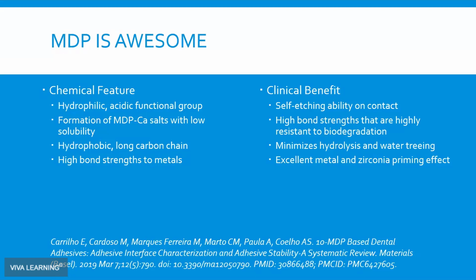Now, one key difference that has been shown is etched versus unetched enamel. Prepared enamel is fine, but with unprepared enamel, you'll see a dramatic improvement in bond strength if you etch the enamel prior to exposing it to MDP. The MDP calcium salts that are formed between the tooth structure and the adhesive have low solubility, which, as I mentioned earlier, helps to have high initial bond strengths that are resistant to breakdown. This long hydrophobic carbon chain minimizes hydrolysis, so you don't suddenly have whole fillings falling out. You don't have crowns just falling off for no reason. It's super stable due to the hydrophobic aspect of it. And of course, the high bond strengths to metal are exhibited in its tenacious grip, most popularly to zirconia nowadays, but all metals as well.